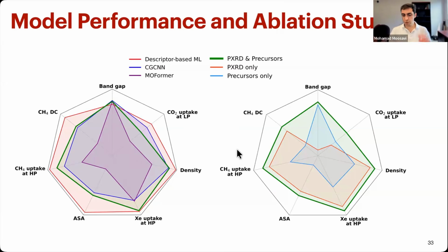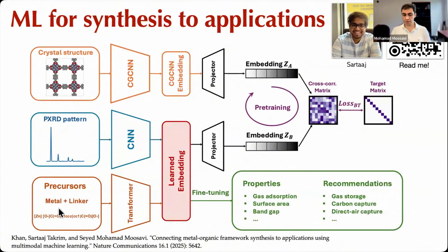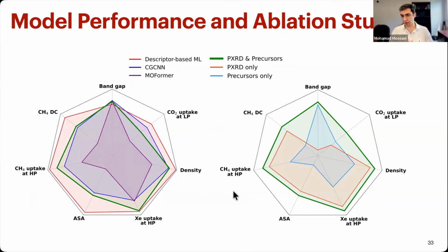And interestingly, these two modalities, PXRD and precursors, capture different aspects that matter for our application. PXRD is very good with the spacing of atoms in 3D space, so it's basically capturing the pore geometry and pore volume related properties. On the other hand, precursors capture the chemistry and related properties. So if you remove one, for example, PXRD only, it fails very badly predicting band gap because it's highly chemistry dependent. On the other hand, if you remove precursors, you see that band gap is still okay, but the geometry dependent properties are really poor now. So this is showing us that the combination of these two can be very powerful.